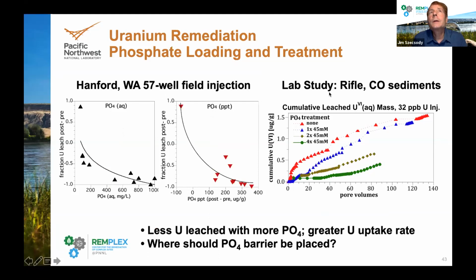Now in a lab study with Rifle sediments, we're doing something similar, but it's a little easier to show because they're defined lab experiments. This is cumulative uranium in column experiments. The red is untreated, and then we had low, medium, and high phosphate treatment, and you can see more phosphate, less uranium leach. This sediment had uranium in it, but I was also injecting uranium into the column because that's what occurs in the field.